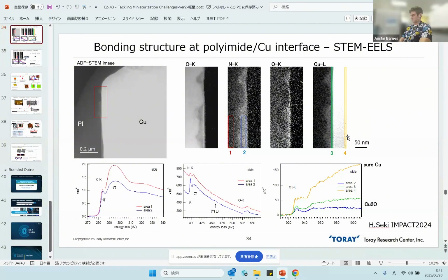So if we can remove the surface copper oxide layer, maybe we can also suppress copper diffusion. So maybe this is the solution of this peeling problem, the suppression or removal of the copper oxide layer. I believe so. Interesting.